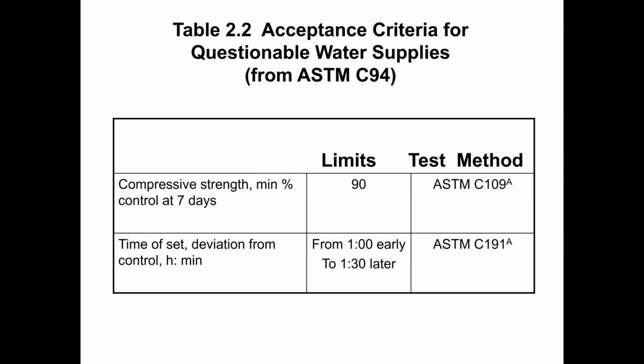So long as the compressive strength of the questionable sample is within 90% of the control sample, and the set time of the questionable sample is from 1 hour earlier to 1.5 hours later than the control sample, then that is an indication that the questionable sample of water may be acceptable for use in concrete. Right? Passing these two tests does not make it acceptable. It just leads us to the next set of tests that are shown in PCI MNL 116.